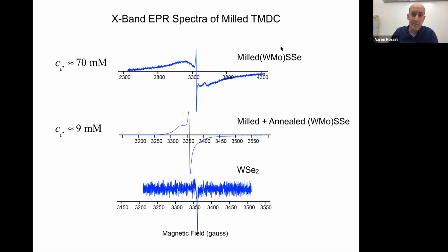So if we look at the milled sample of tungsten molybdenum sulfide selenide, formed by milling tungsten selenide and molybdenum sulfide, we see this very broad EPR signal that's over 2,000 Gauss across, and we estimate the unpaired radical concentration is about 70 millimolar. Annealing does remove some of those unpaired electron spins, but you still have a concentration of about 9 millimolar. When we try to do DNP, we don't get any DNP enhancement from either of these samples. It seems like those unpaired electrons created during the milling process just react with and reduce or oxidize the DNP polarizing agents, and that stops DNP from working. At least it's one of the reasons why DNP doesn't work on those mixed systems.